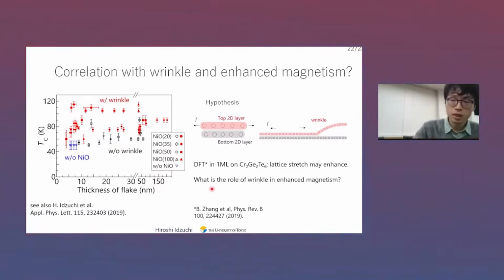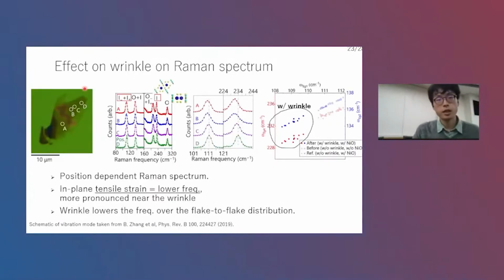So we have characterized by Raman spectrum. Raman spectrum shows very good features, and peak position varies with place, and this indicates actually near this wrinkle lower frequency. That means tensile strain. And also we have measured a lot of samples and show some correlation. That means basically with wrinkle we have a lower frequency.